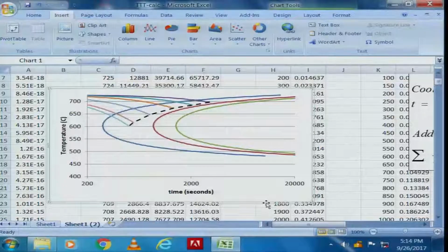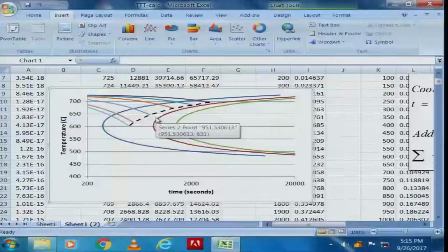And you will see these are for different, decreasing values of B, these are the cooling rates, and they are all terminating at the point where the summation term goes to almost 1. Hence, if I join all those with a smooth curve, this becomes my CCT line. So, what this is telling me is this line outside here is 1% transform and this is the corresponding CCT line for 1% transform. As you can see, there is a significant shift of the CCT curve from the TTT curve towards the right to longer times, and they are shifted to somewhat lower values of temperature as well.